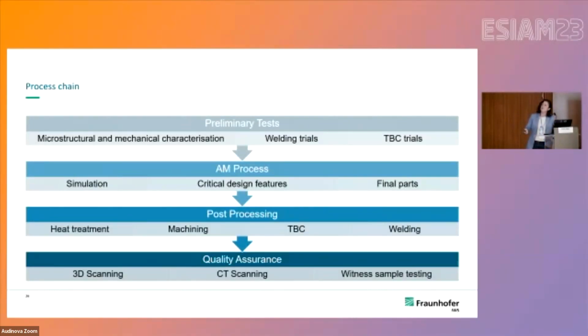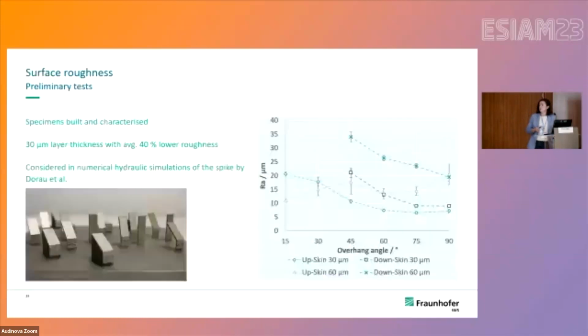For the bigger aerospike rocket engines, we are combining conventional manufacturing, so welding, and AM due to the issues with the size. So in some cases, we are printing two parts separately, the rod and the tip, and then welding them. And to increase the high temperature properties, we realized there is some kind of limitation with Inconel, even if we submit it to heat treatment for higher temperatures, and therefore we also introduce in some thermally critical areas a TBC coating, thermal barrier coating, sorry, to increase the resistance against thermal issues.